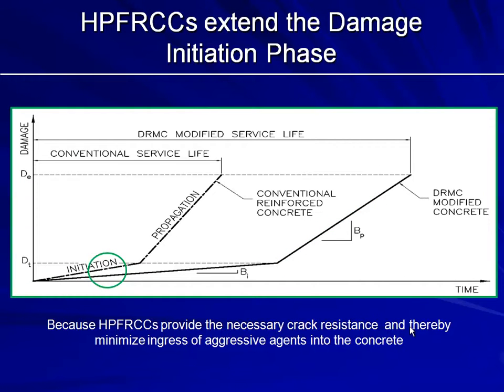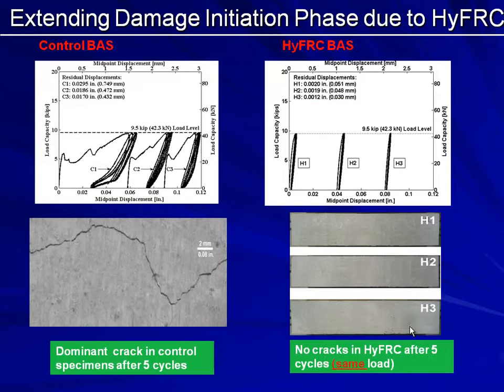Now, in regards to the initiation, why do you modify the initiation? The initiation is really caused by cracking, and that's exactly what the attributes are of high-performance fiber-reinforced composites. They are very resistant to cracking. So this is why you can delay that kind of damage initiation. As you recall, I had that picture up before, that you have here a conventional bridge approach slab versus a high-performance fiber-reinforced bridge approach slab. And the cracking here is completely different. Same load level, you have very dominant cracks. That means all the aggressive agents, chlorides, everything can infiltrate your concrete, whereas in this case here, they can't. That means the initiation phase is being enhanced.